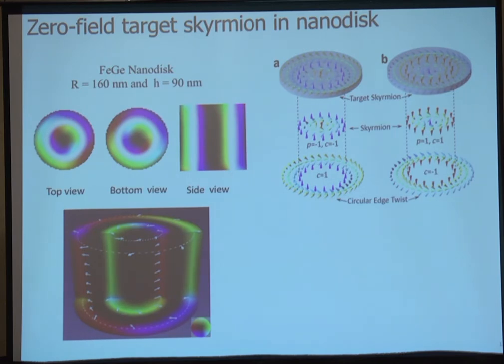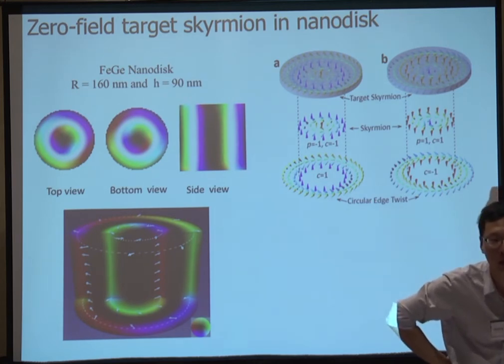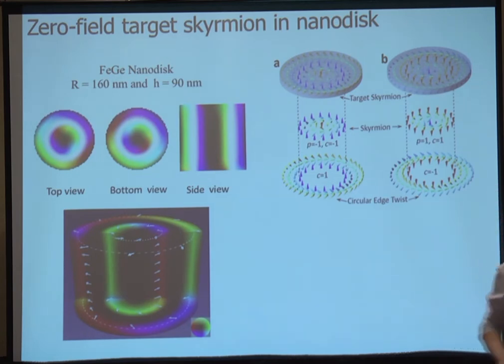You showed that you have these excitations and in the different layers it looks different, right? Do you see also along the Z direction a static configuration of twist? The twist only appears around the boundary. There is no twist in the interior. In the interior, it's just a very boring, very simple structure. So what breaks this twist? That is because of the imbalance of the DM interaction. This applies in many confined geometries, because outside this structure there are no spins, and the DM interaction is not balanced. That's why there are some additional structures.